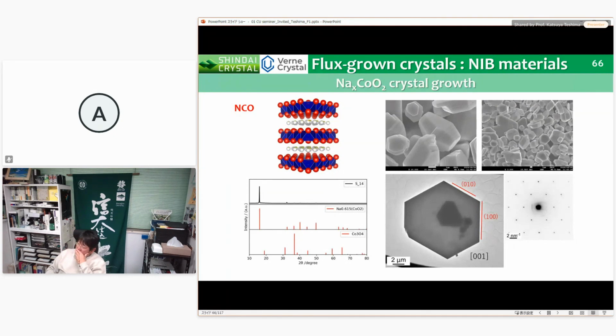Furthermore, the crystal stacking direction was consistent with the stacking direction of the two-dimensional layers, indicating that this shape is favorable for the diffusion of sodium ions.